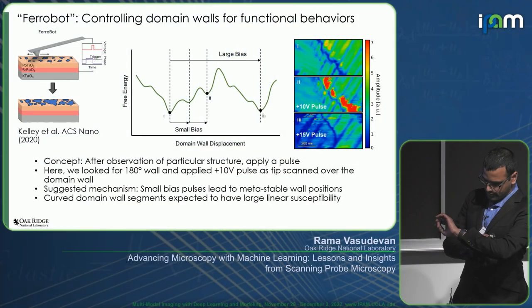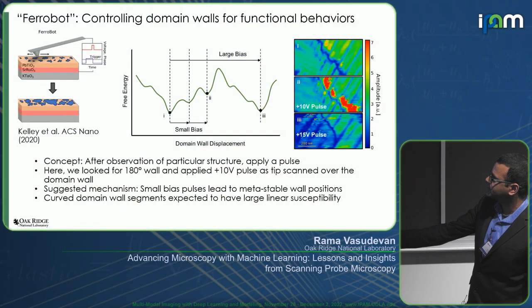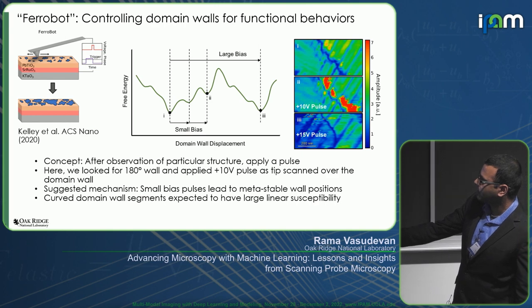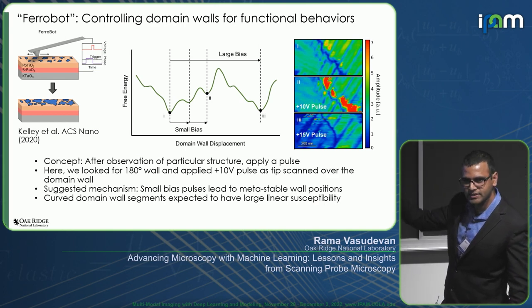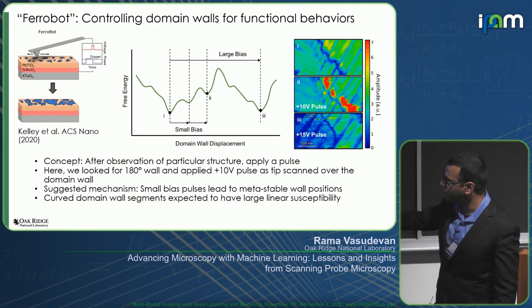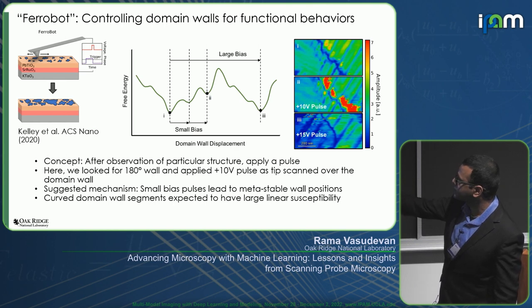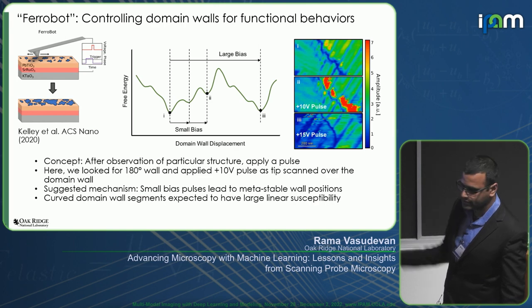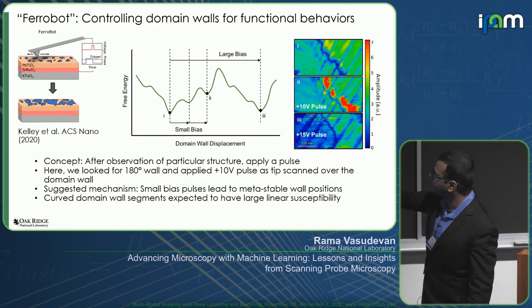So what we see here is a so-called ferrobot system, where we take our AFM tip, and again, it's the same kind of FPGA device that I showed before, and we scan across this particular domain wall in a different sample. This is a lead zirconate titanate sample. And every time the tip scans across this interface, it's applying a single voltage pulse. When it does this across the image, you can see after we've done this that there's a region of high or enhanced response on this side of the domain wall